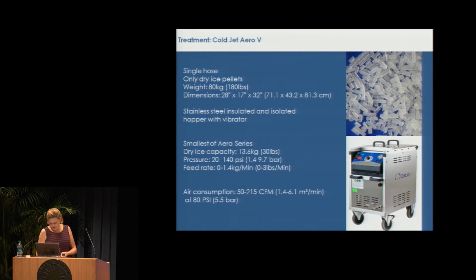And it also has a container of, I thought it was 30 pounds. Yeah, 30 pounds dry ice capacity. So the container can hold 30 pounds of dry ice pellets. The pellets we had were the 3 millimeter pellets. Nowadays there are also smaller pellets, down to 1 millimeter, but back then you could only choose 3 millimeter pellets.